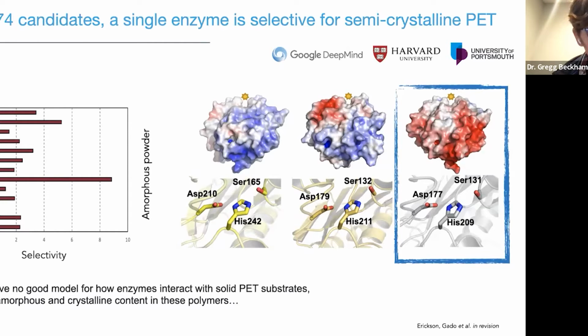And what I'm showing you here are selectivity differences in the enzymes from amorphous powder to crystalline powder. And what you can see, this is just for a small subset, but this is basically the take-home message for all of this. We found only a single enzyme that has actually preferential activity for a crystalline powder, and this was really exciting. And this is the enzyme in particular, and we were interested in why it has better activity on crystalline powder. I don't have the answer for you, but one hint that we do have from the structures,